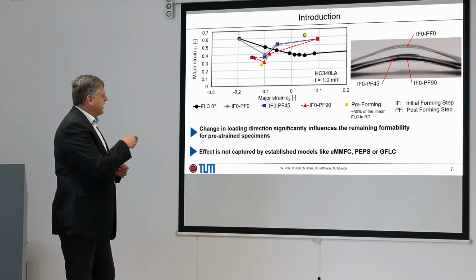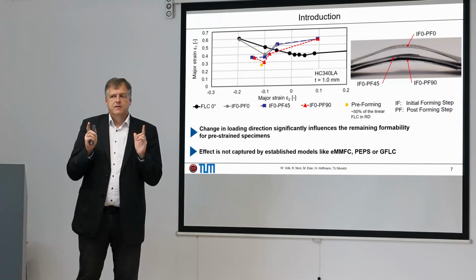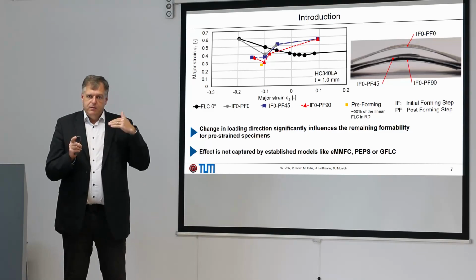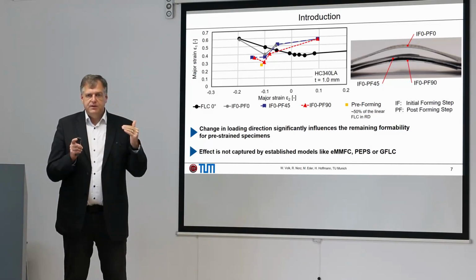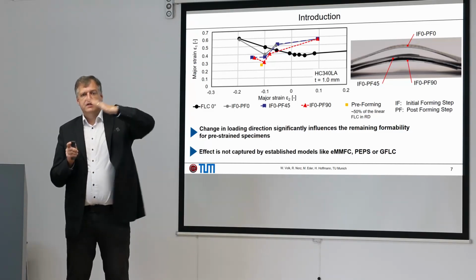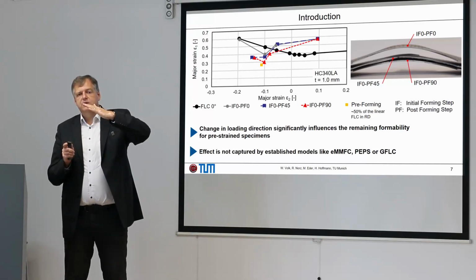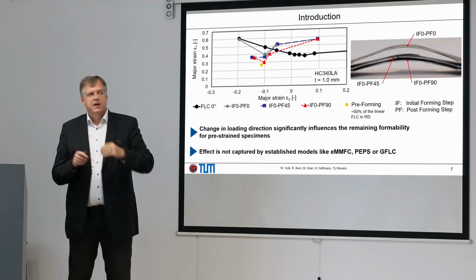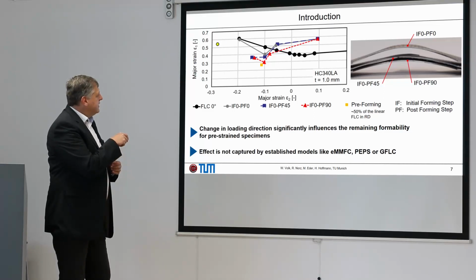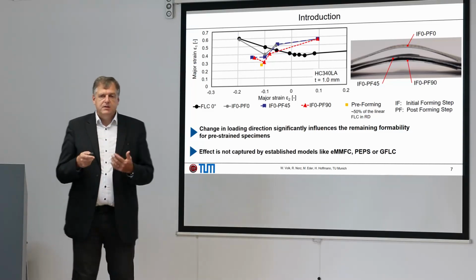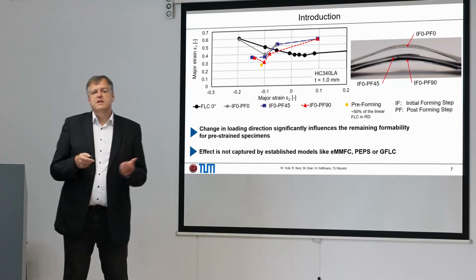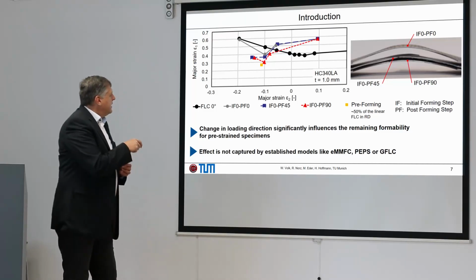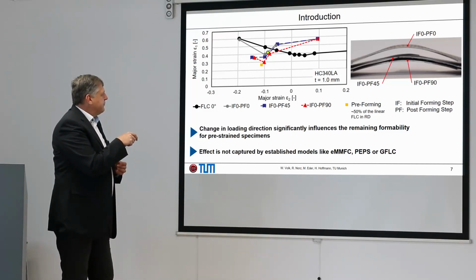I'll start with 90 degrees. It's the red curve. The only difference, we start preforming at 0 degrees, and then just turn around by 90 degrees, and then do the second step. And you see here the totally different material behavior. That we are losing much formability just by changing the rolling direction of the second step. For 45, it is somewhere in between.